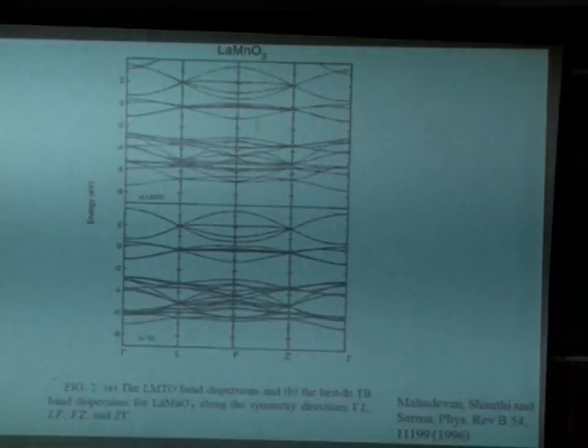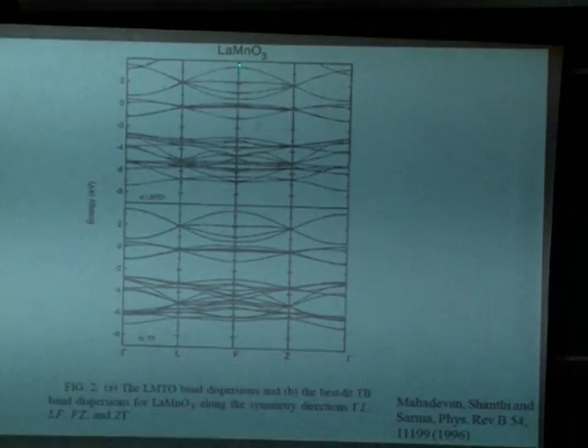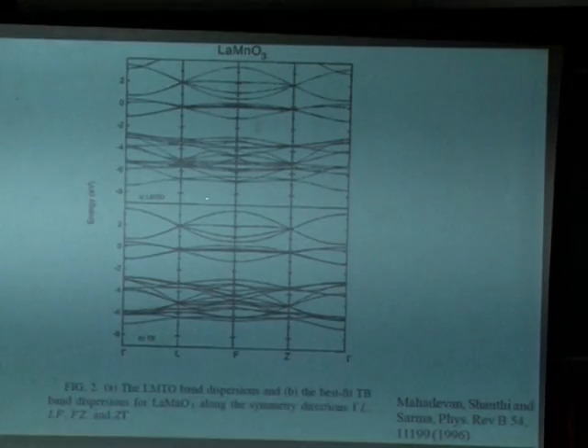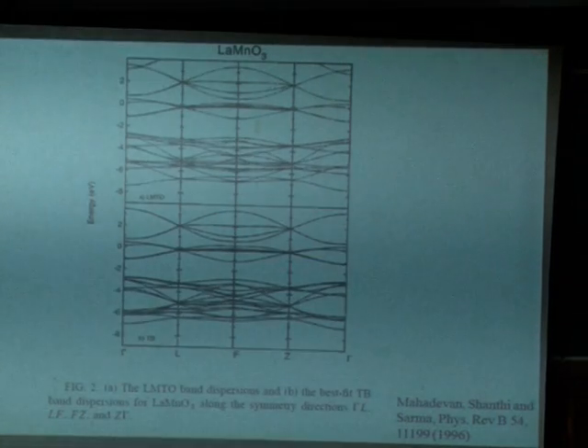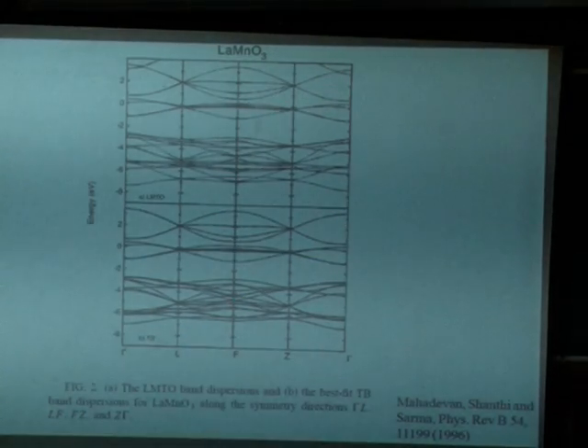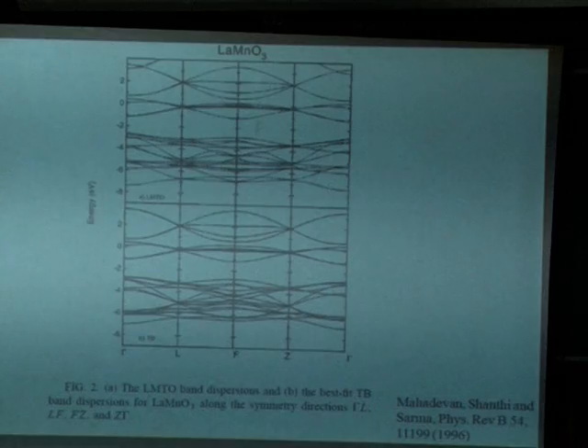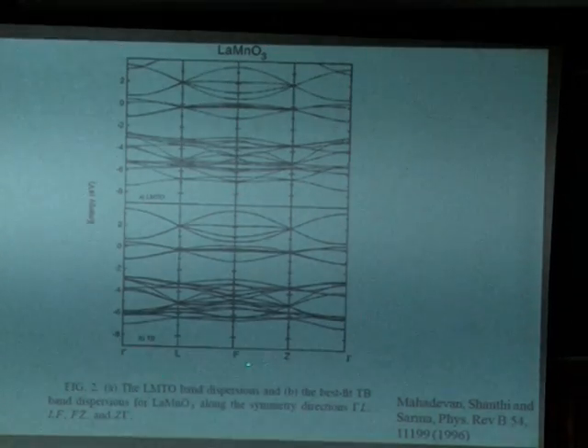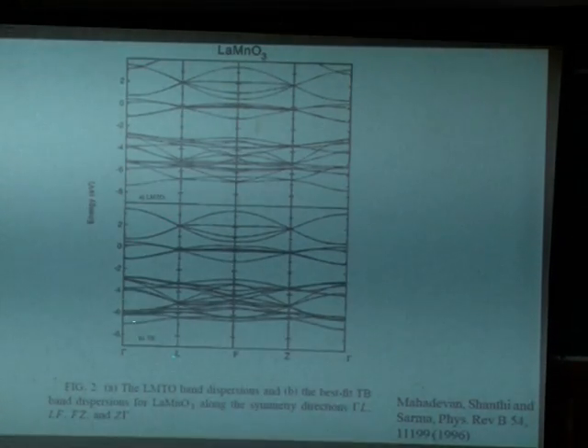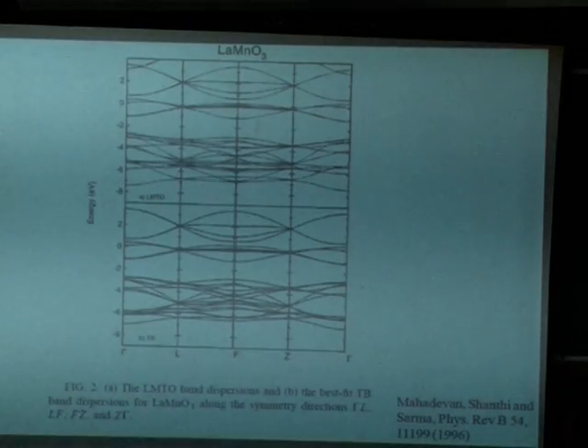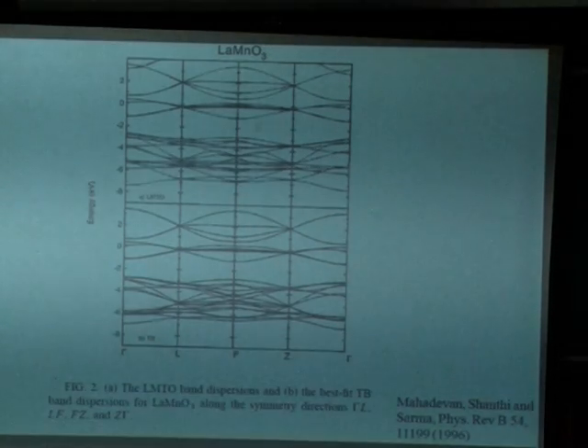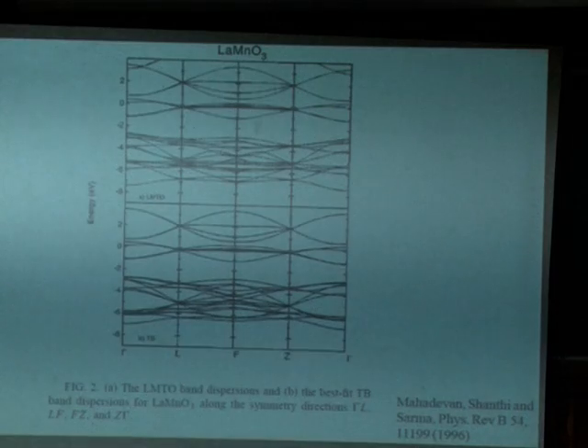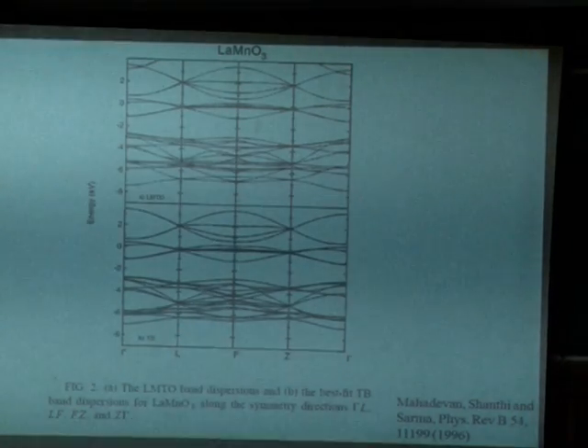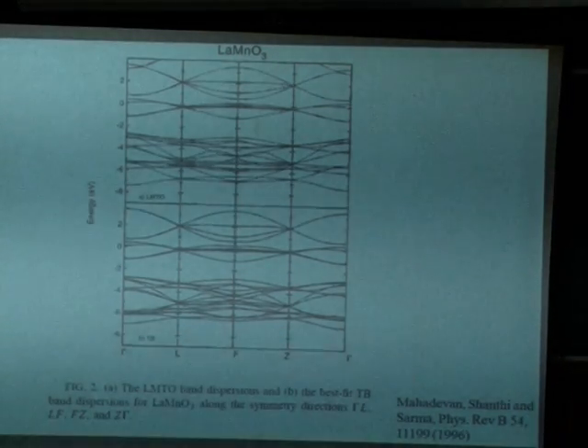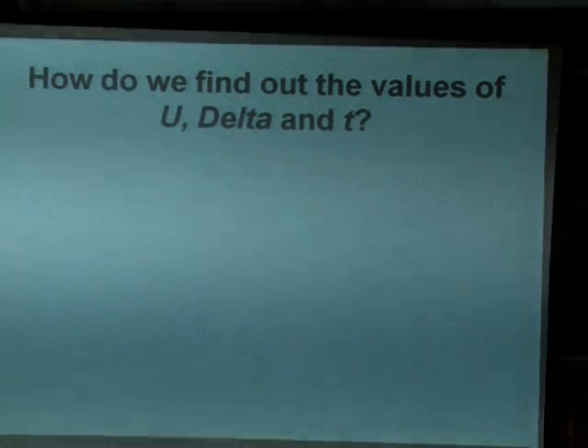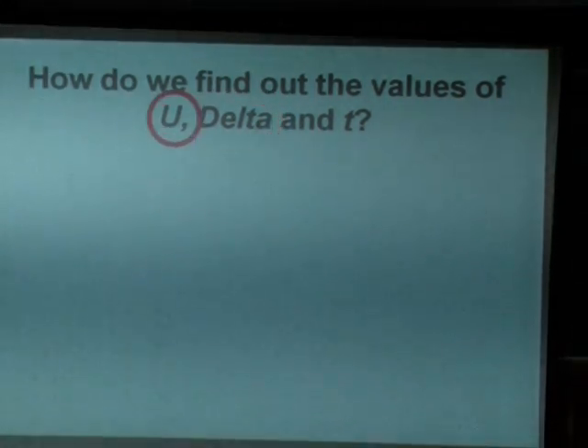Here is an example, and you find it very difficult. LaMnO3, this is the truth and this is the tight binding model. And you can see that they look almost identical. So I now know from this model all the manganese d, oxygen p hopping. This was created with a tight binding model that only had manganese d and oxygen p, and oxygen p and oxygen p interactions. So all the hopping interactions are defined. So T is known. How do I determine U and delta?